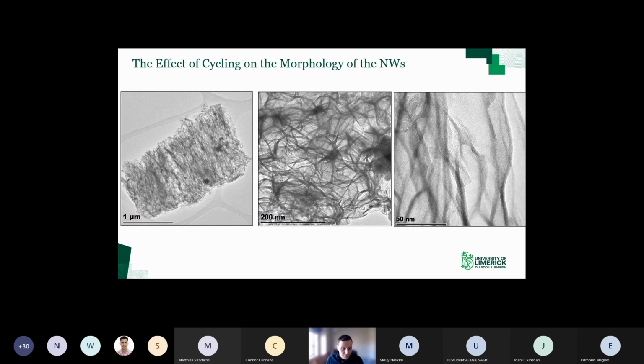So if you look at a high mag image of that on the TEM, it's very obvious now that the nanowire morphology is gone. And as you zoom in, you can see this ligament structure has formed.